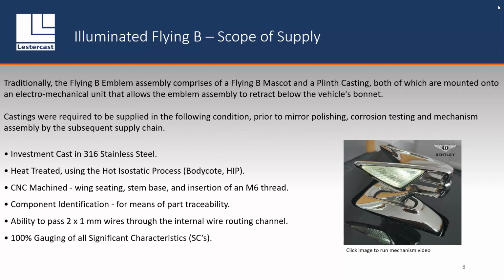On the previous emblem, the condition has always been mirror polished, corrosion tested. No different with this one. So our criteria was 316 stainless steel, heat treated using a HIP process, CNC machined. They wanted full traceability of every casting down to melt, material lot. So we had to come up with some means of putting traceability on both the plinth and the emblem.